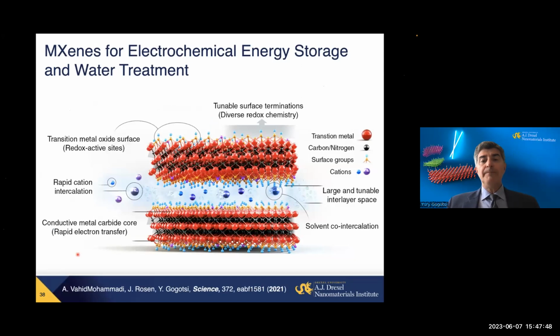And of course, if you know the structure, if you know the composition, if you understand the chemistry of the material, you can always find applications. For example, we can use a controlled gap for water desalination and purification. We can use it for transport of ions in batteries and supercapacitors. We can use the transition element on the surface for redox energy storage, because those are vanadium, titanium, niobium, the same elements that you use in batteries and supercapacitor electrodes that can reversibly change their oxidation state. And the conducting carbide or nitride core can quickly conduct electrons, providing rapid electron transfer. So you look at the properties and then try to determine the application.